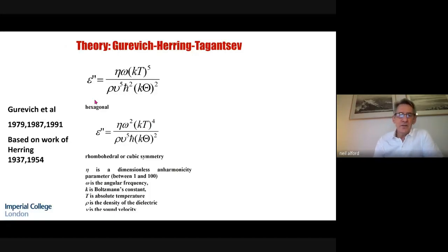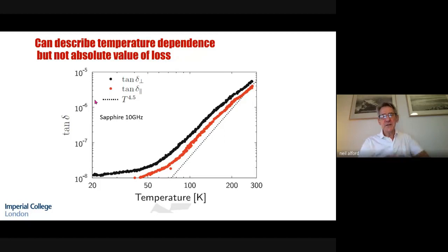Now, Gurevich, Herring, and Tagantsev all produced theories of dielectric loss. They were mainly based on the work of Conyers Herring back in 1937 and 1954. And what we can see here is that the dielectric loss should go as a fifth power of the temperature. And so if we have a look at that, we can see that it can describe the temperature dependence of the dielectric, but not the absolute value of the loss. And so we need to start looking at how we can manage that.